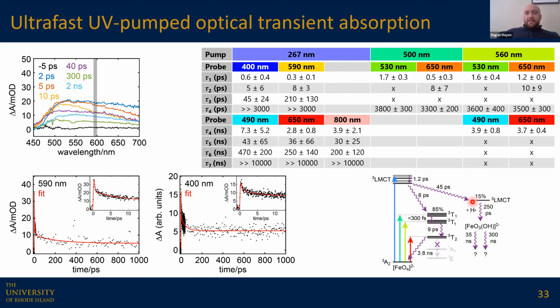And so we do have these additional time constants that we're not really sure about. We think these have to do with the subsequent photochemistry of this iron 5 species. It's known that the truly metastable iron 5 species is actually equivalent to abstracting a hydrogen atom from the solvent by the excited ferrate 6 to form the ferrate 5 with a hydroxyl ligand. And so we think that could be this 250 picosecond time constant that we're seeing. We've done some isotope substitution studies, but haven't really been able to confirm that. But we were able to pretty definitively, I think, figure out this side of what's going on in ferrate 6.